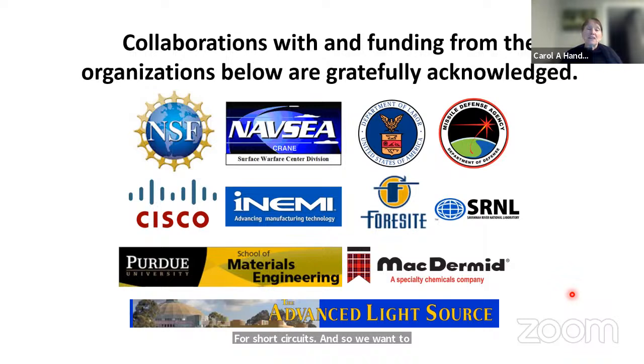And basically what we found over the years is that because dislocations are involved in this and they can accumulate, we can't stop them from forming except by putting an even stronger capping layer on the surface. And that capping layer is a very strong polymer system. So I have a circuit board. I take the whole circuit board and I put it into a vapor phase reactor with something called parylene, and it then coats all the surfaces.